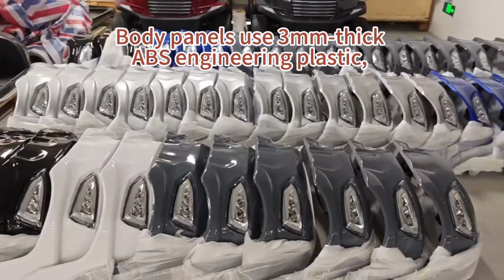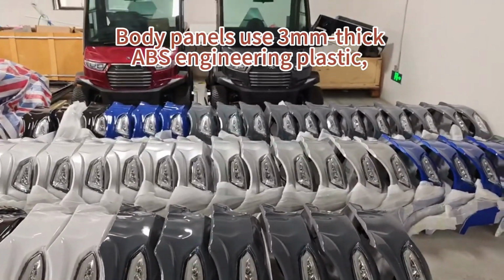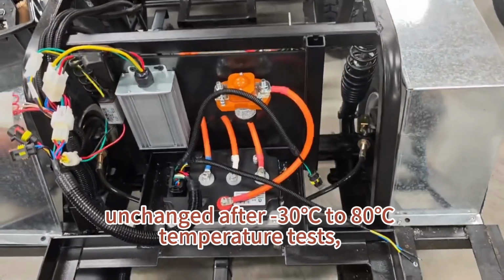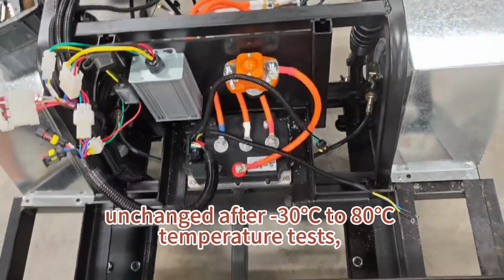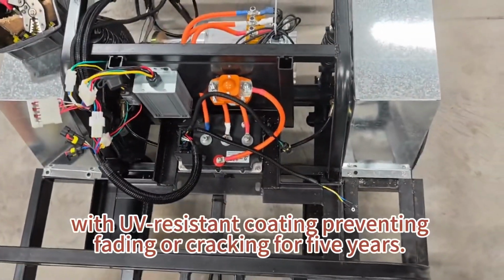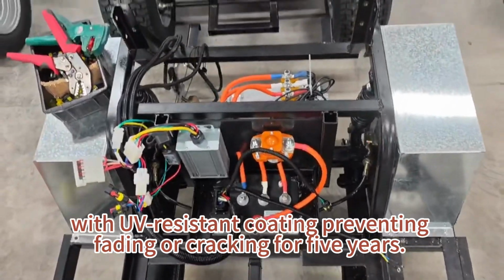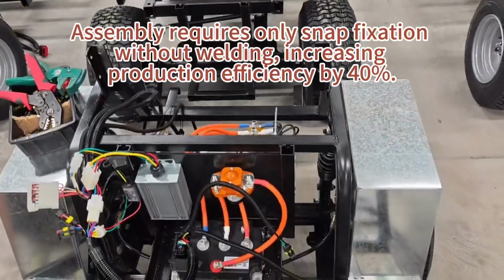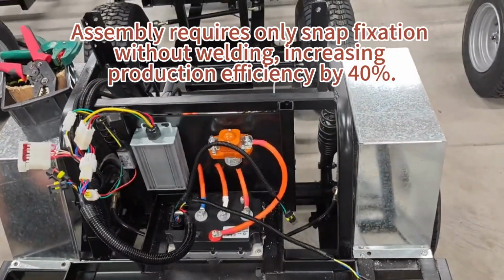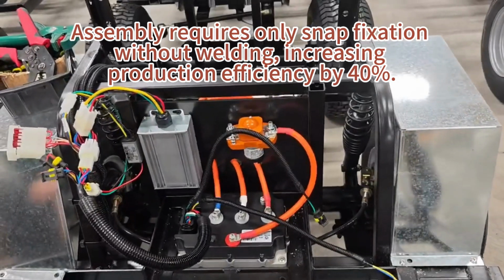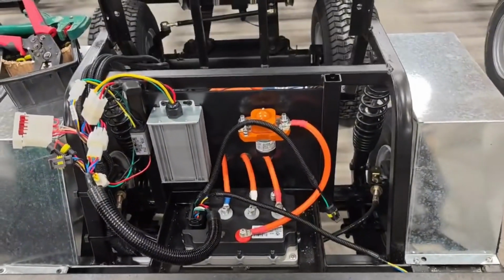Body panels use 3 mm thick ABS engineering plastic, unchanged after -30 degrees Celsius to 80 degrees Celsius temperature tests, with UV-resistant coating preventing fading or cracking for 5 years. Assembly requires only snap fixation without welding, increasing production efficiency by 40%.